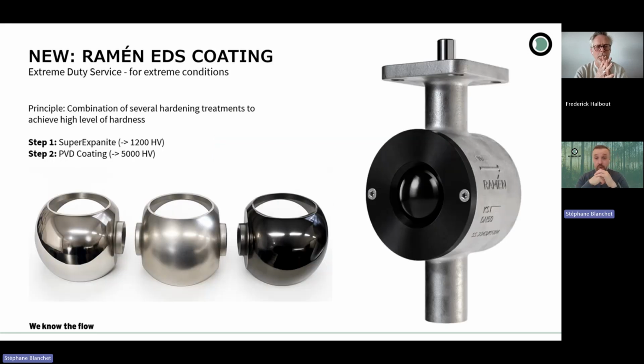And this is where we came up with this new coating, because we tried a lot of different solutions, and this is the one with which at the end we got the best result by far. And this is the one that we're actually talking about right now and that we are releasing into the market. It is our EDS coating, that stands for Extreme Duty Service. And it is a combination of several hardening treatments that end up with a hardness of up to 5,000 Vickers. And you see on the left actually these different steps. So you see 3 ball sectors. On the left, this is a stainless steel one. And then on top of this one, we put some super expandite treatment that already increased the hardness quite a lot. And in addition to that, which makes this solution very robust, is the PVD coating, for which we can get up to 5,000 Vickers.